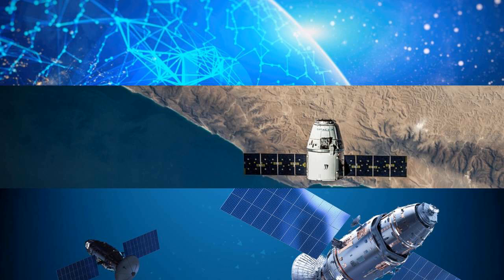That's a very great question. BepiColombo is really the textbook case where you need two very different coatings working together. On this mission, we've used Magic Black, which is Acktar's ultra black coating. It's tailored for the visible near-infrared nanometer range used by star trackers and optical instruments. It has about 1.2% reflectance and basically eliminates stray reflections that could blind the detectors. It's thin, highly emissive, and resistant to radiation and atomic oxygen, which is why it's basically a default coating for star trackers on the European market.